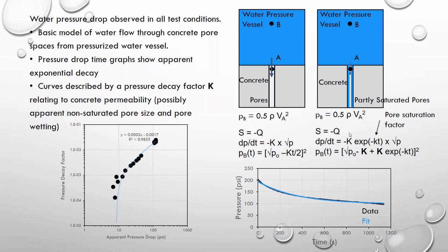So we modify this equation to have a term where we look at what I call a pore saturation factor. That is, how much does that pore get wet with time? So we include this exponential drop with time, saying that the area of pores, whatever it may turn out to be, will get smaller and smaller with time as the pores saturate. We can solve this differential equation, again with energy and mass balance, and we see the fit data, the blue line, starts to fit very, very well with the actual data points. And so this decay factor K is what we're getting here for our graphs, and we think it's a good way to characterize these curves.